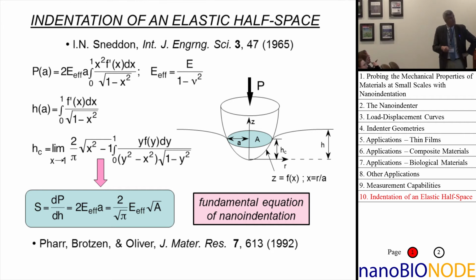times the radius of contact, which then translates to an equation that looks like that in terms of the area of contact. And so this equation, stiffness equals 2 over square root of pi, E effective times the square root of A, becomes the basic equation that we use to analyze a whole lot of stuff that's going on in nanoindentation. And the idea is simply this, that S is measurable from the force displacement curve. And if we can measure S from the force displacement curve, then if we know the modulus, then we can get the contact area, and that gives us something about the hardness.